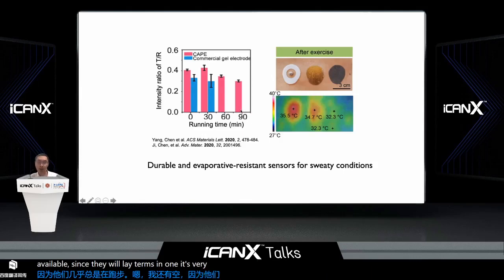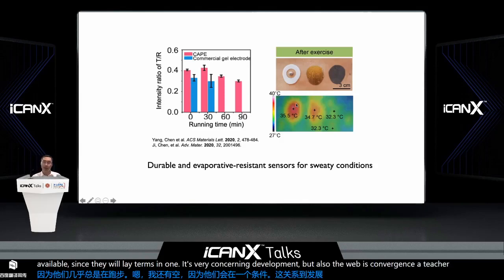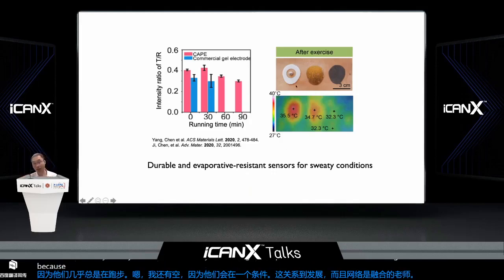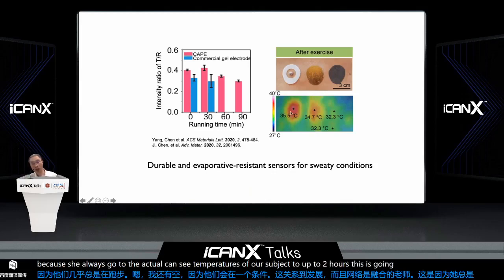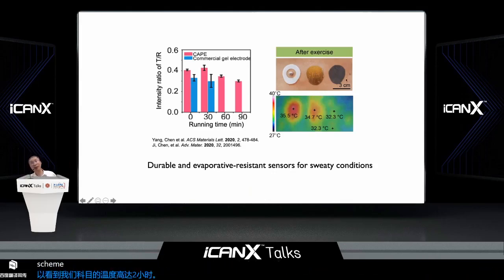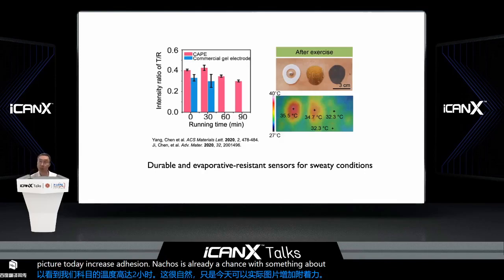Not only this one, we can also develop electrodes that attach to our skin for continual running, because skin is always evaporating. It's a kind of liquid electrode. If you use a normal electrode, you can see the beginning temperature is about 32 degrees. After 2 hours of running with commercial gel electrodes, the skin temperature increases dramatically. But our electrodes really solve the evaporative resistance issue.